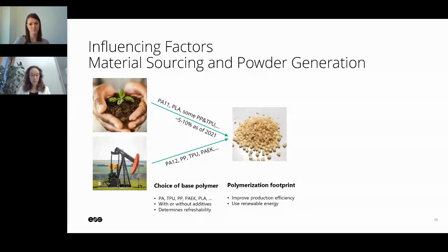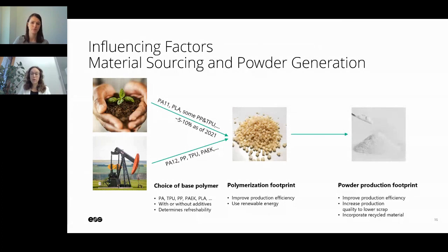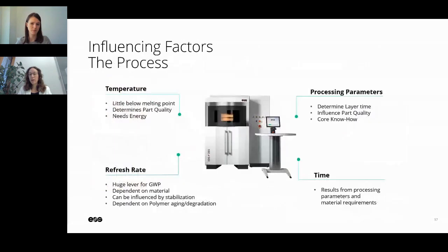Now we have our base polymer, and we have to make that base polymer into a powder and sometimes even modify it, for example, by compounding additives or fillers. For the powder production, the same accounts as for the base polymer production. I can improve my production efficiency. I can use renewable energy, but also increase my production quality in order to have lower scrap rates. And I have the potential to incorporate recycled materials. So there are quite a few levers in order to have a more sustainable material, but you have to have the right one.